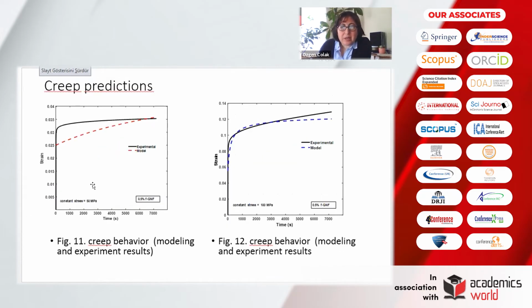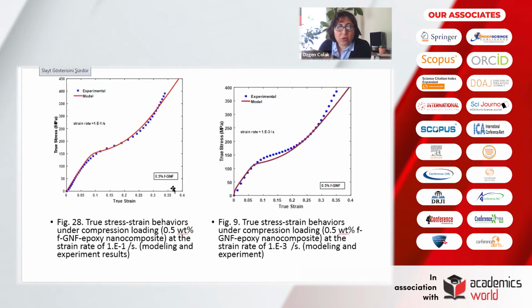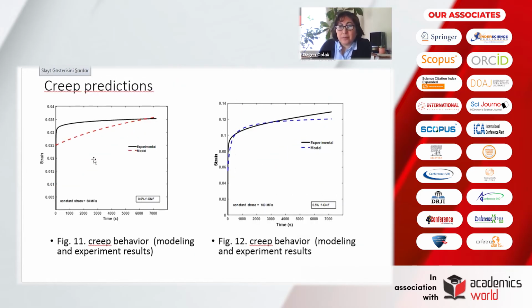And in this slide, you can see the creep experiments. As known, creep behavior depends on stress level. So that's why we perform the creep experiments at 50 megapascal and 100 megapascal. If we look at where 50 is, it is in the elastic region and 100 is close to the yield point. So even though we are in the elastic region, we can see the effect of the stress on the creep behavior. And the creep time for these experiments is 2 hours.